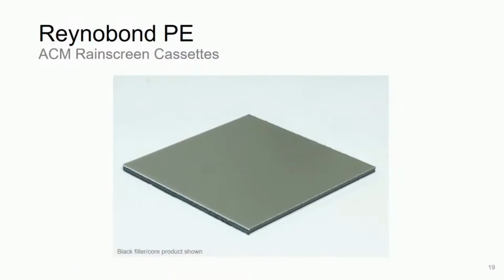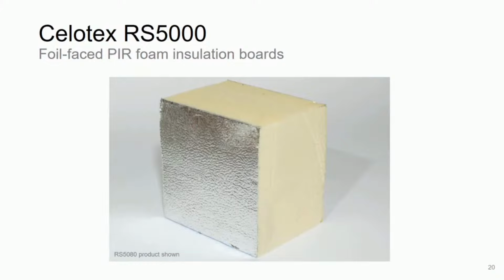Reynobond PE ACM, or aluminium composite material, which is shown here. In basic terms, this product consists of 2 0.5 millimeter skins of aluminium, either side of a 3 millimeter thick core of polyethylene. Celotex RS5000 insulation board, which is shown here. I'll refer to this simply as RS5000 throughout this presentation. This product consists of a polyisocyanurate, or PIR, polymer foam core, faced on both sides with a thin, unperforated aluminium foil, which is only a fraction of a millimeter thick. I've performed experiments on both the 80 millimeter thick RS5080 product and the 100 millimeter thick RS5100 product.